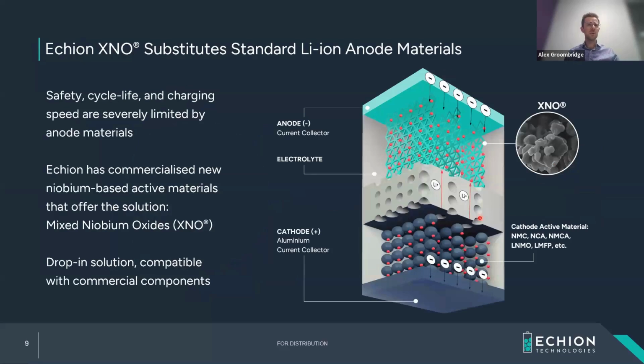So as a battery as a whole, I've got a little schematic on the right here for those who are less aware. For lithium-ion batteries, we're operating with liquid lithium-ion, organic electrolytes. We have our anode materials, cathode materials sandwiched together. And what we've been working on at Echion is changing that fundamental anode active material away from your graphite, your silicon, LTO, to a niobium-based chemistry. And at Echion, we call this XNO, mixed niobium oxide. By changing it here, we managed to get around these fundamental limitations.